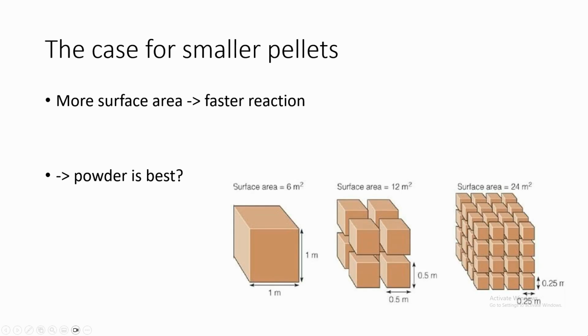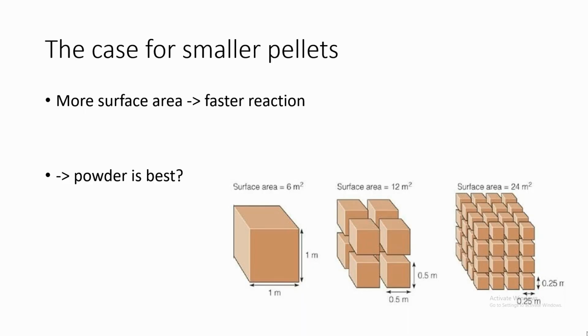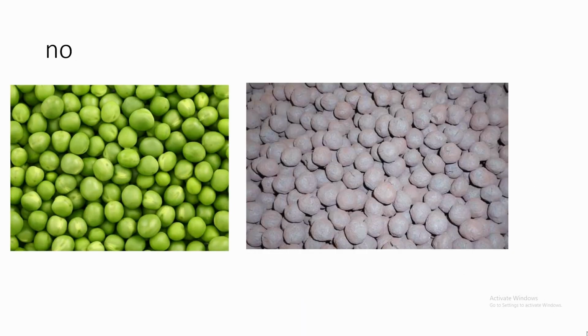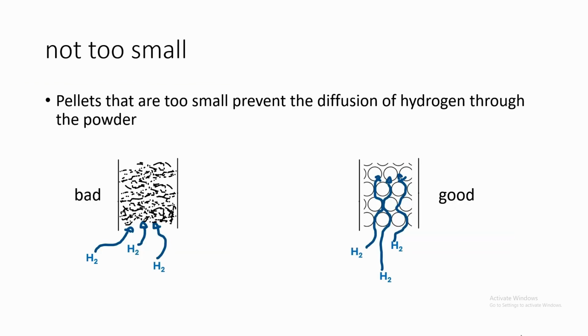For the pellets, right, there's an argument to make them as small as possible. The smaller they are, the bigger the total surface area is, which means that more hydrogen contacts more iron oxide, which causes the reduction as a whole to happen faster. That would mean a super fine sand would be best then, right? Because maximum surface area? It turns out though, that in real life, they use around pea-sized pellets. This is because if you have a dense wall of powder, the hydrogen can't budge its way through it. You need small gaps in between the pellets so that the whole stack of material can react with the gas.